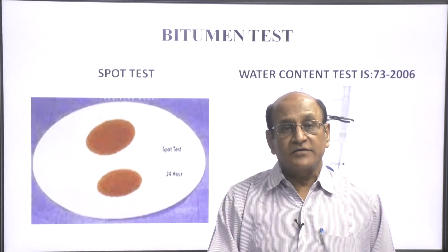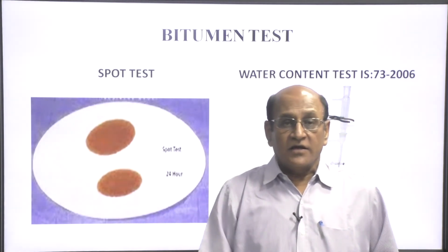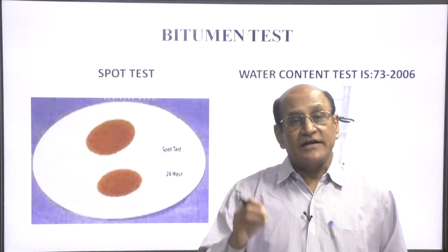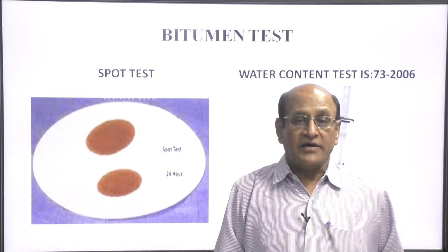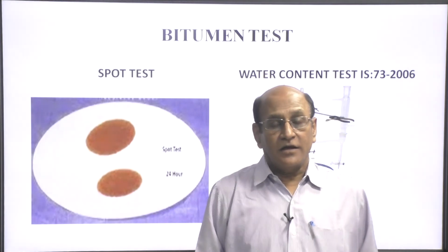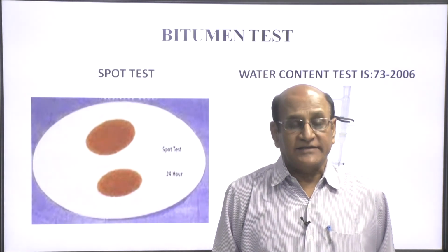For the water content, the sample contains some water, which is heated, and the vapor is collected and cooled down again to make water. That gives the water content, which should not exceed 0.2%.